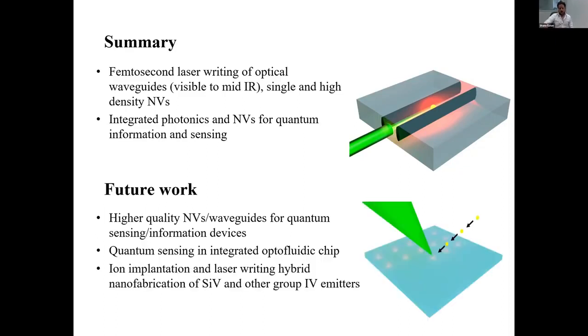In addition, along with Alexander Kubanek, but also Paulo Oliveira, we're looking at a hybrid technique. So one disadvantage of femtosecond laser writing is it's a microfabrication technique. And so we cannot place NV centers near the surface at nanometer depths below the surface of the diamond. And for a lot of quantum sensing applications, you need these NV centers to be very, very close to the surface, again, nanometer depths.